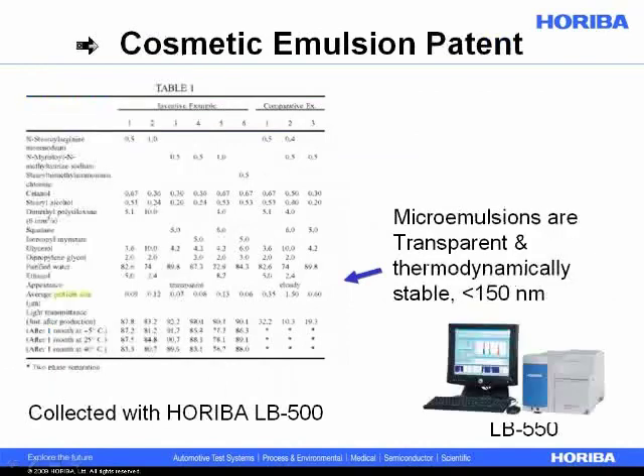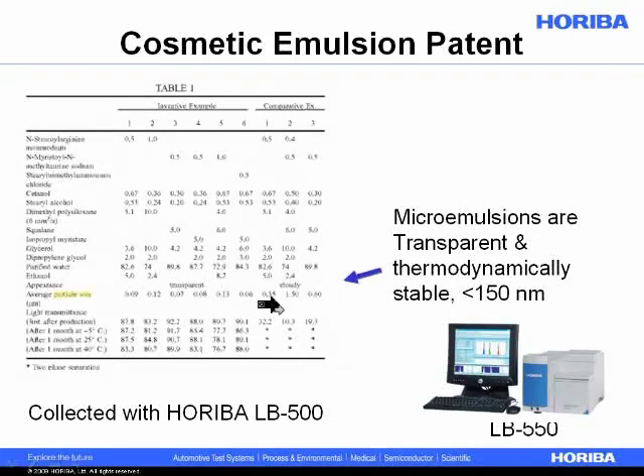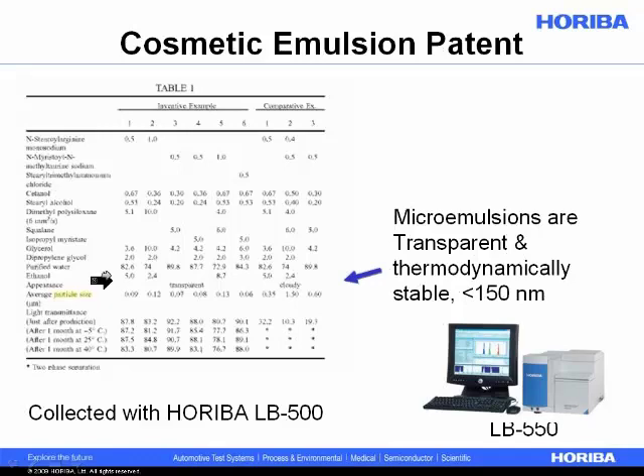I went to the Internet and started doing some searches for emulsions and cosmetics and found a patent where they note they did the particle size measurements using the LB500, a dynamic light scattering instrument made by Horiba. What you see is a comparison of the inventive material to a comparative material called 'Cloudy,' where the droplet size of the emulsion is in the range of 0.3 up to about a micron. But with the inventive product in the patent, they're saying all particle sizes are down under 120 nanometers and they have a transparent material.